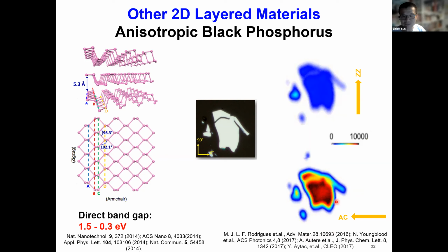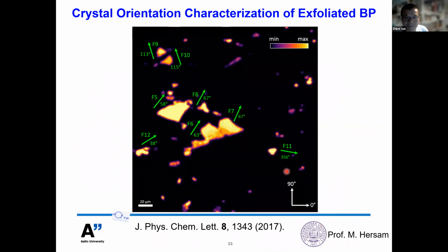I also mentioned that similar results have been reported by Cristiano inside black phosphorus with different thickness. But as I mentioned, because of this anisotropic response of black phosphorus to the polarization of the incident light, we are able to use third harmonic generation to measure the crystal orientation of the exfoliated black phosphorus flake. So this is our result.